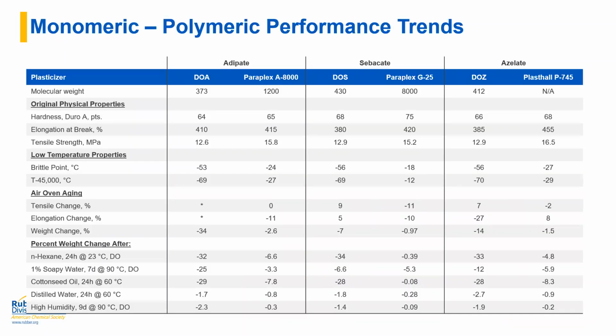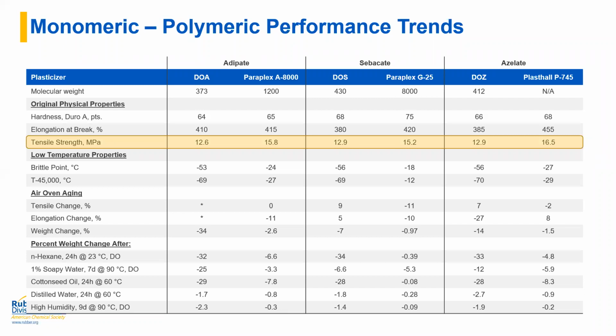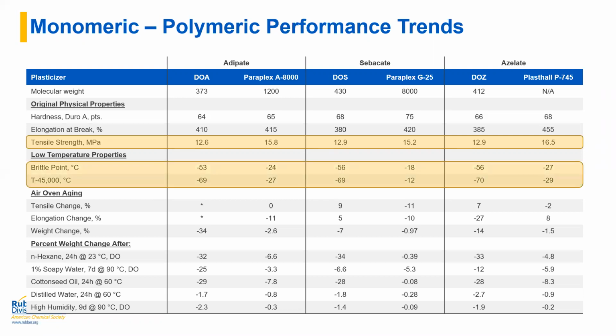So there's a lot of data on this slide, but I'm going to draw your attention to a few things. This is more so that if you want to look back at this later, you can look at the numbers a little bit more closely. This is to show within chemistry families, so adipates, sebacates, and azelates, the difference between a simple monomeric of that chemistry and then a polymeric version of that same chemistry. The first thing that is very clear of the difference between the two is overall tensile strength. Polymerics are not going to be as efficient at the same loading level as a monomeric would. So you see a lower tensile strength with the same loading level of a monomeric versus a polymeric within the same chemistry family. The next thing though is the low temperature.